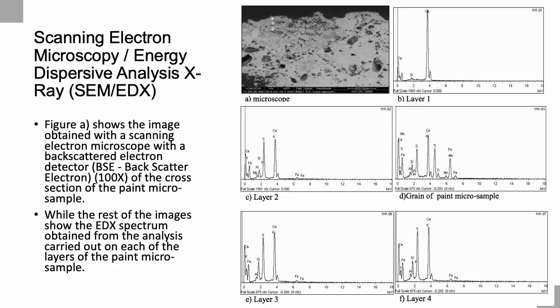Scanning electron microscopy, energy dispersive X-ray analysis. Figure A shows the image obtained with a scanning electron microscope with a backscattered electron detector of the cross-section of the paint microsample, while the rest of the image shows the EDX spectrum obtained from the analysis carried out on each of the layers of the paint microsample.